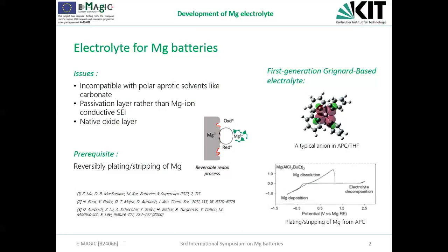I mean, the first generation of magnesium battery that could deal with this problem, or realize the reversible magnesium stripping and plating, is to apply a Grignard-based electrolyte. We know that Grignard agents are reactive, and they could condition the moisture and also some oxidant species in the electrolyte solution, and could also somehow clean the magnesium surface. And with the addition of the chlorine species, we have the well-known APC electrolyte reported by Professor Aurbach's group.